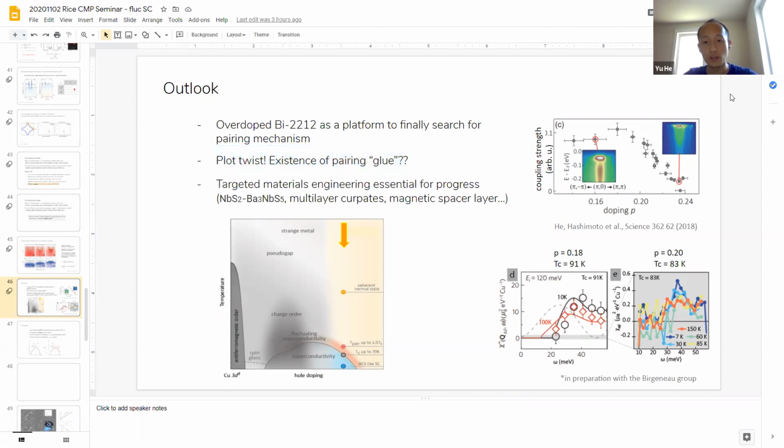The reason was because we checked the most prominent electron-phonon coupling type in this overdoped region, and it's almost non-existent at 22% doping. And then we also measured the magnetic excitation in those systems, and it's more than an order of magnitude weaker than what you would have in a near optimally doped sample. So the two leading candidates of low energy pairing boson are seemingly out of the picture. But nonetheless, it's contrasted with the observation that the system seemed to still follow what a weak coupling theory would predict, a 2 delta over kBTc ratio, with the normal state being metallic. Then these two observations seem to contradict each other. Not to say that pairing glue is not there, it's just we're struggling to find that mysterious boson if it were to be in place.